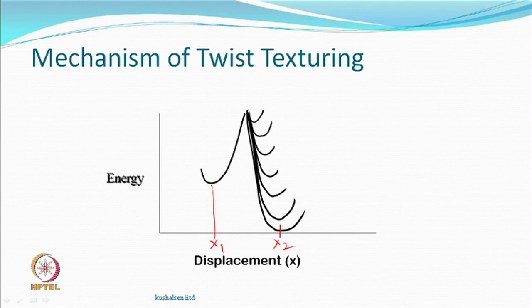Our starting position was an untwisted multifilament yarn. There is another position where you have done some setting — in this case, maybe it was a thermoplastic yarn and you did heat setting, so the energy kept coming down and became more stable. At point X2 it is an untwisted multifilament yarn, so it is a textured yarn.